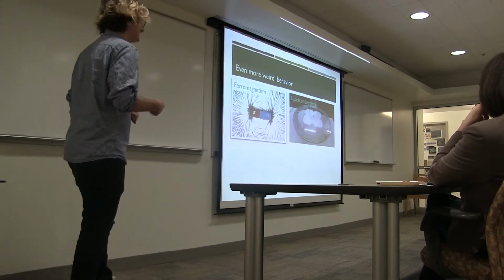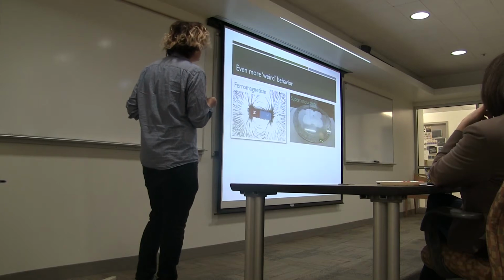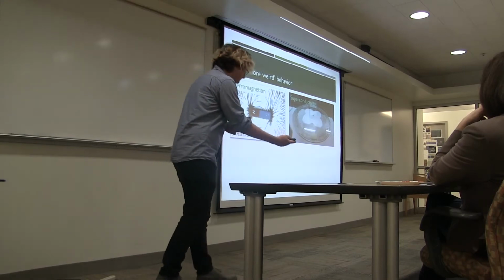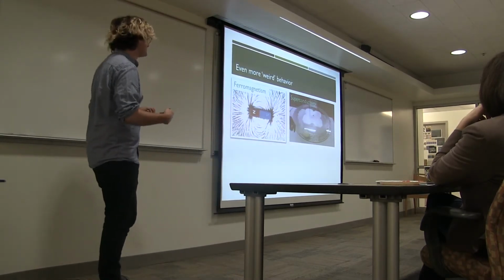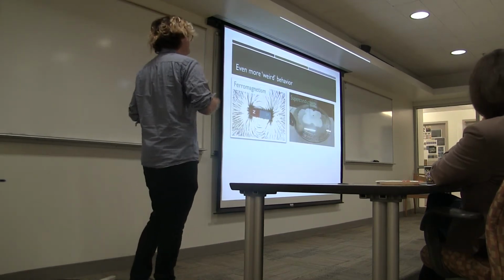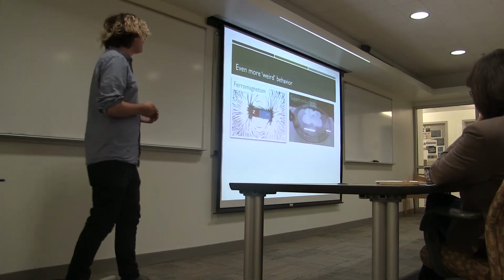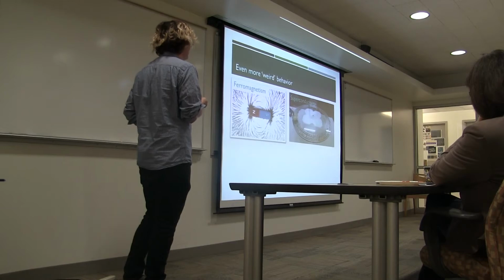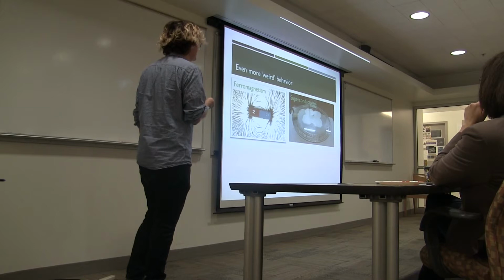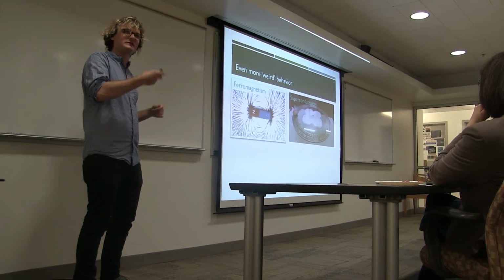Superconductivity is another example of interesting stuff that happens in materials. Here I'm showing an image of a superconducting puck that's levitating over a track made of permanent magnets. Superconductors have two interesting properties. Their resistance goes to zero, which means that you're able to flow an electrical current without heat dissipating. And secondly, they expel magnetic field lines in something called the Meissner effect. That's part of the reason why this puck of superconductor is levitating: the superconductor is expelling magnetic fields, and therefore there's a repulsive force.